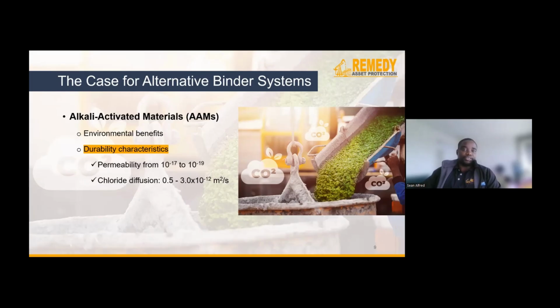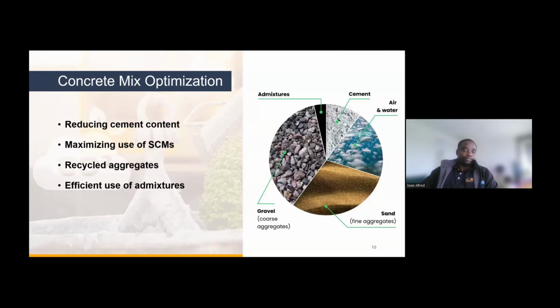And existing research work also indicates that these alternative binder systems exhibit a high resistance to chloride ion penetration and the characteristics that we look for, like using high SCM replacement levels. But to date, you find that there's still caution to use high percentage replacement of SCMs because there's limited field data to assess whether observations from accelerated tests are comparable with actual field conditions.